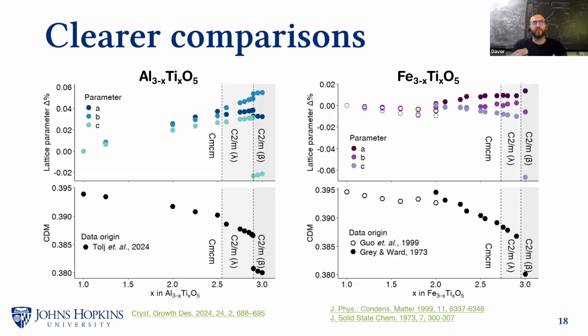At a certain point, the concentration of these dimers becomes critical, and there is a phase transition to this beta phase. So CDM allows us to see what's actually happening, or at which point there is some critical change. But of course, to understand why it is happening, we need to go more deeply into the material. But that's kind of the point: to be able to analyze whole families of materials and find these discontinuities, which can then be further analyzed.